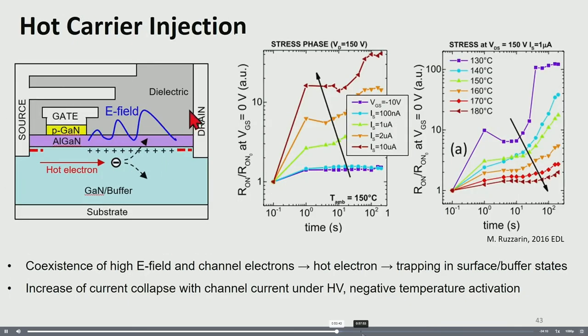Hot carrier injection is another important trapping mechanism in gallium nitride. If there are channel electrons under a high lateral electric field, these electrons get accelerated, and these energetic electrons can be trapped in the surface state or the gallium nitride epi. To study this hot carrier injection effect, the high voltage semi-on state stress setup can be used.